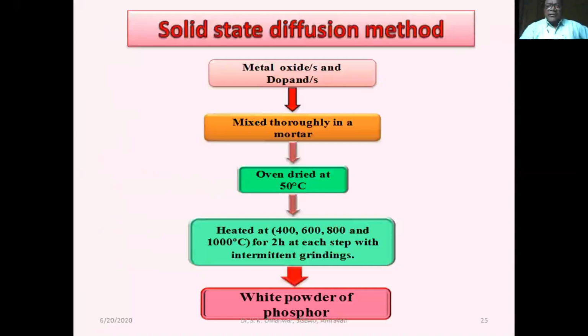Solid state diffusion method, the flow charts are there. One can see the flow chart. Metal oxides and dopants are mixed thoroughly in the mortar, oven dried at 50 degrees centigrade, and subsequently at 400, 600, 800, and 1000 degrees for 2 hours at each step, with intermittent grinding also.